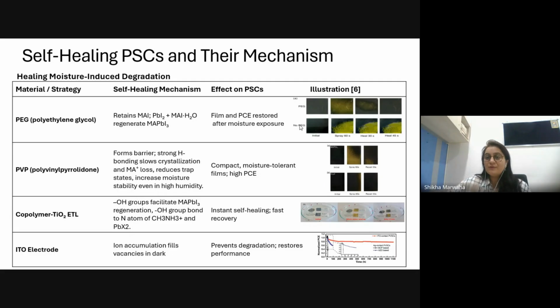So here, if you can see, the first figure is when we are using PEG in our precursor. Even after 45 seconds, first of all, there is some degradation, but with time it heals itself. In the first figure, when we had PEG, the first and the last figures are almost the same, so they are retaining their phase. Because phase, we can see with the naked eye, there will be a change in the color. So yellow color is basically showing that the phase has been changed. But initially, yes, there was some phase change, but then it has self-healed.